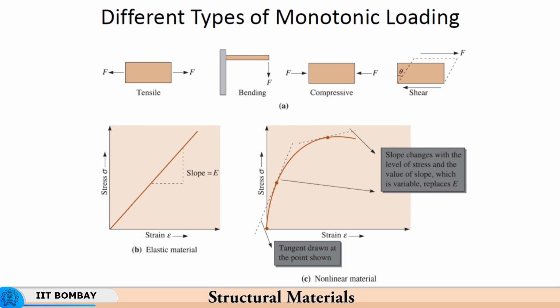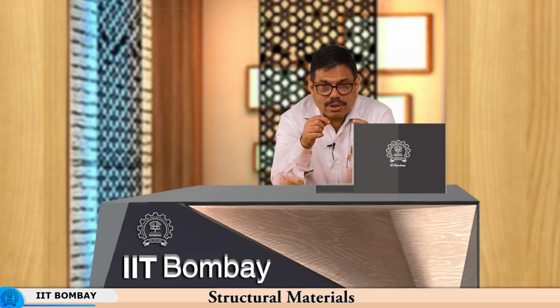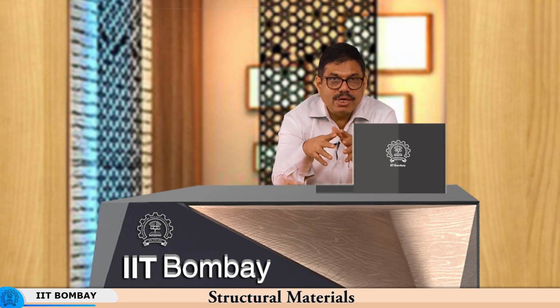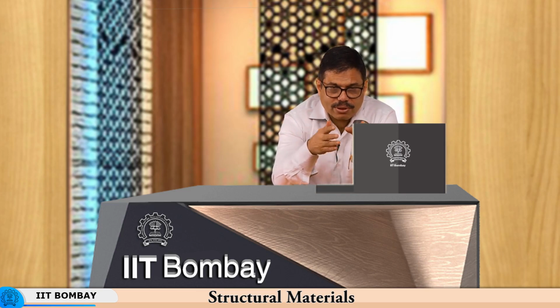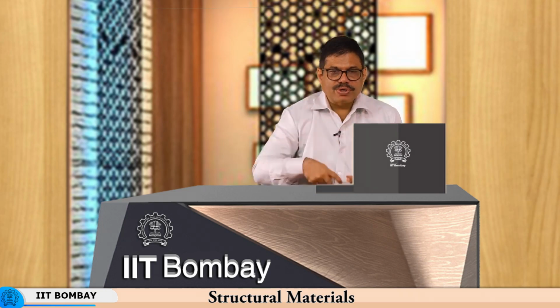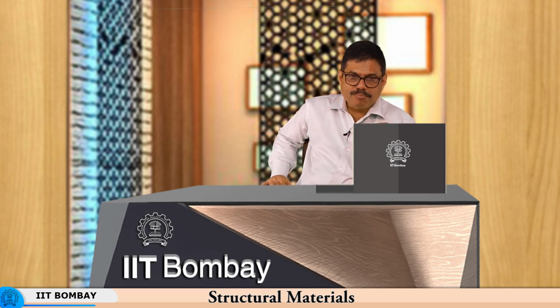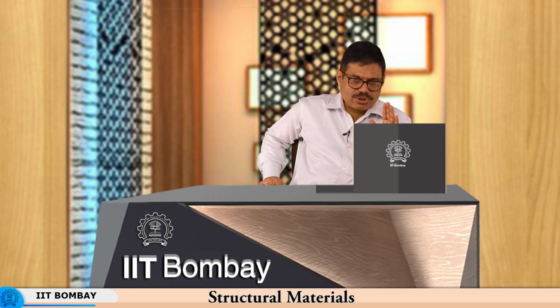Now, when we try to make the product, when we try to make the entity that is supposed to withstand structural loads, for example, a turbine blade or a turbine itself, the turbine during functioning will undergo elastic deflections, but when you actually want to shape the turbine blade from, let us say, a single crystal to the kind of shape of the turbine where you have different angles, entry angle, exit angle and so on, there you need to deform it, and therefore you need to take it beyond the yield point of the material. So, elastic deflection is not enough. Elastic deflection will get removed or it will be recovered completely, but now what you want to do is, while manufacturing the turbine blade, you need to change the shape of the material permanently, so that the blades have a shape giving the right kind of entry angle and the right kind of exit angle for the gas or steam or whatever fluid that you might be using.